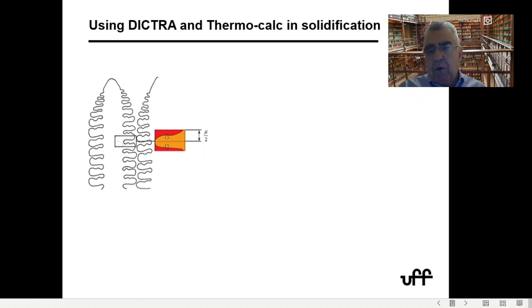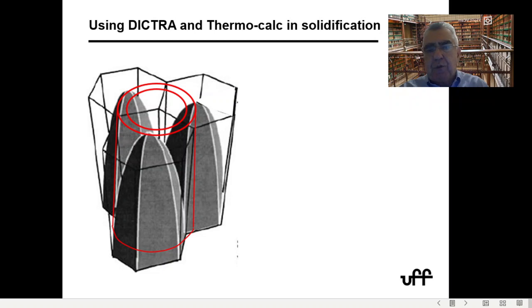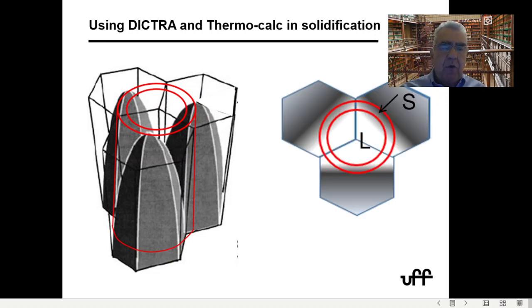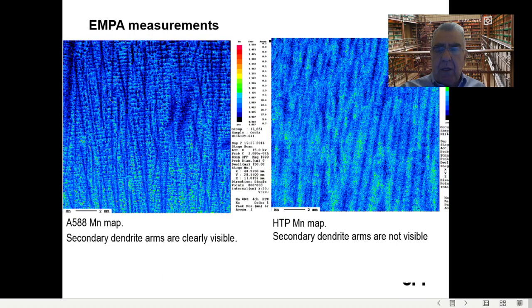So what we do is we take the secondary arm spacing to model the segregation. And then, since DICTRA can only handle simple geometries, we imagine that this interdendritic space is like the center of a cylinder placed at this position. This is more or less the physical model that we're doing with diffusion. DICTRA can only model diffusion, but it models very accurate diffusion with the proper thermodynamic data and the proper interaction of the diffusing elements. Then we go back to this microprobe measurement, we go back to measuring the steels, what is the secondary arm space, and with this we can derive the cooling rate.